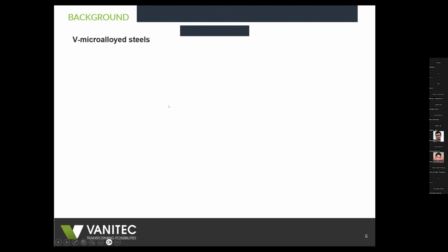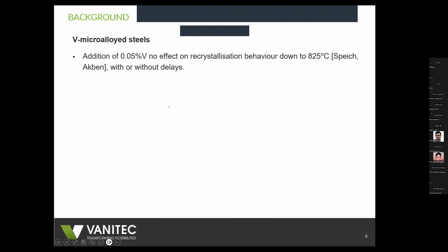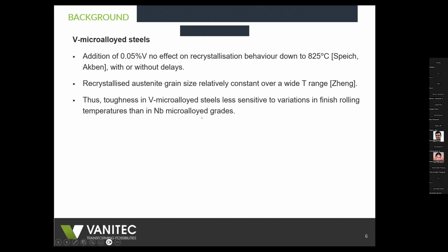Vanadium microalloyed steels, on the other hand, and typically in the region of 0.05% vanadium, have no effect on the recrystallization behavior down to quite low temperatures, up to, let's say, 825 Celsius, with or without delays. The recrystallized austenite grain size is relatively constant over a wide temperature range. Thus, toughness in vanadium steels is less sensitive to variations in finishing and rolling temperatures than in the niobium microalloyed grades.